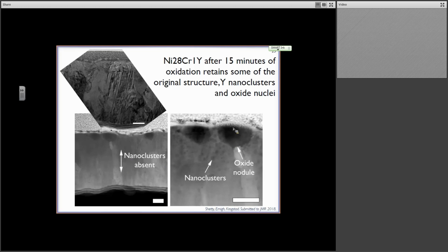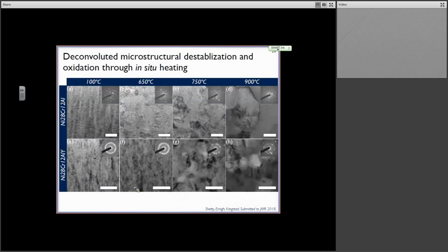And we're also nucleating the oxides, right? This is a nodular-based oxidation mechanism. Without the yttrium, I think I'll show you later, it's also oxidizing, but it is very focused on the surface, and we don't see this sort of nodular growth. And so it's quite interesting because we expected to see a continuous oxide scale here, but that's not what we're seeing necessarily. So the mechanism of oxidation is also a bit different. So we have these nanoclusters and we have oxidation even after 15 minutes, and we preserve some of the nanostructure.